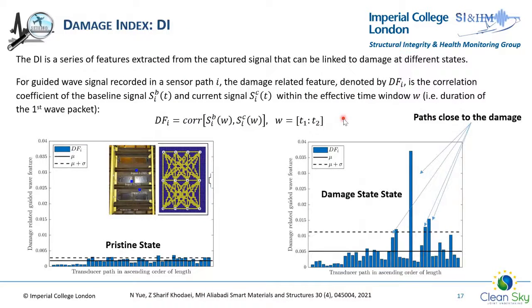So really, the damage detection is based on how you process the data, the pristine and the damaged data. So by introducing a damage index, we developed a threshold for a pristine state, and this is a damaged state. So you put your detectability threshold somewhere that is way above the noise threshold in your data. And also, after compensation for temperature, you need to ensure that the damage is really detected reliably. So this is the first level where we've detected damage based on damage indices.